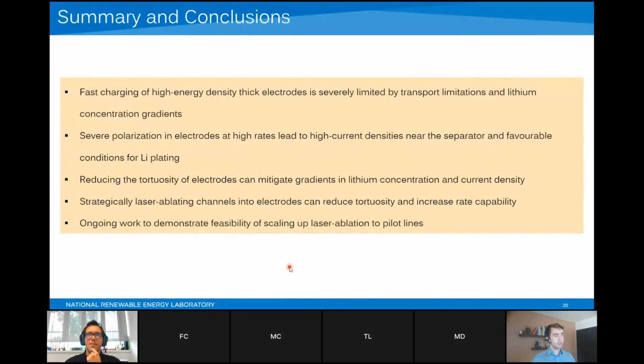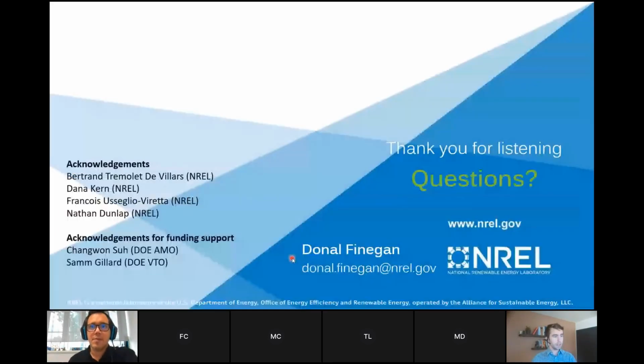Reducing the tortuosity of electrodes can mitigate gradients in lithium concentration and current density and increase the fast charging capability. Strategic laser ablating channels into electrodes can reduce that tortuosity and increase rate capability. And we have ongoing work to demonstrate the feasibility of scaling up laser ablation to pilot lines.